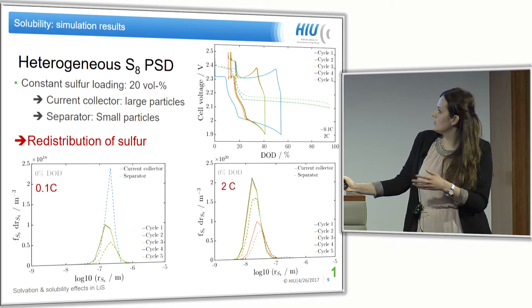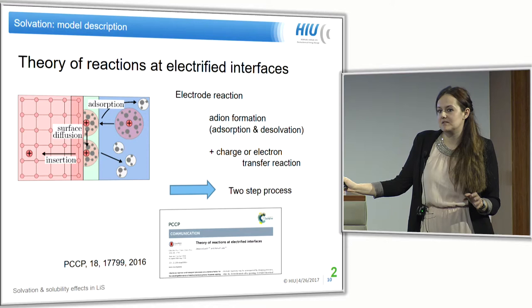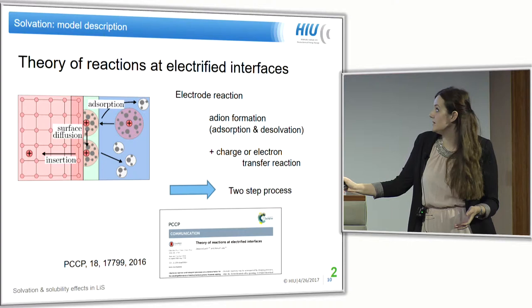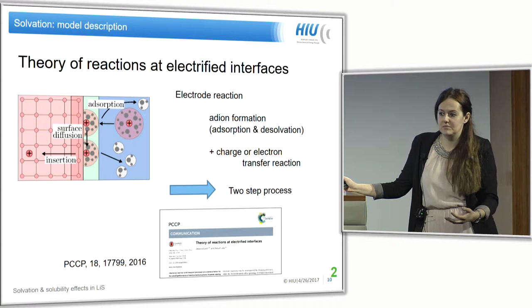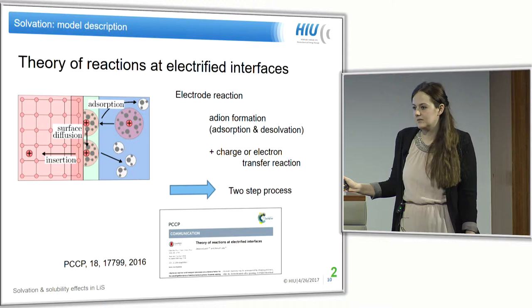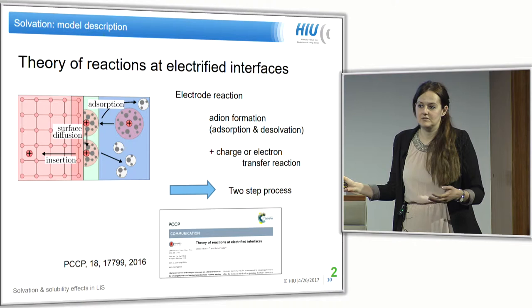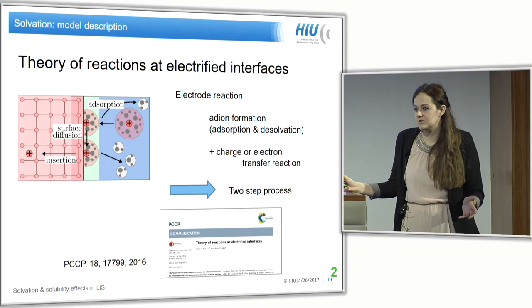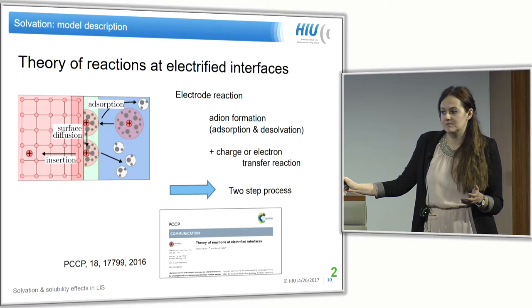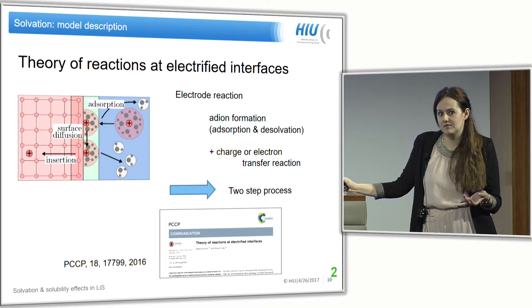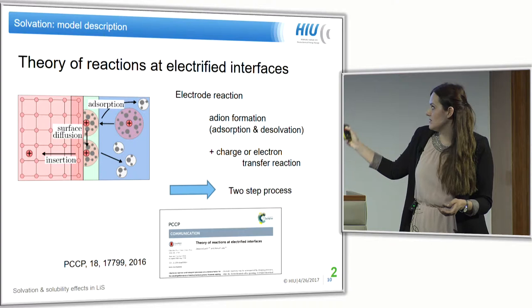Now I would like to change topic to the second part: surface effects, meaning adsorption and desorption. Our approach is to understand adsorption and desorption as a step in the overall reaction mechanism. When an electrode reaction occurs, an ion must reach the surface, possibly undergo surface diffusion, and then the actual reaction occurs. This picture is general — in every case where two conducting phases are in contact, you will have some kind of mechanism. We derived a general theory to describe reaction processes at electrified interfaces, covering charge and electron transfer reactions, published in one paper with a second under review.